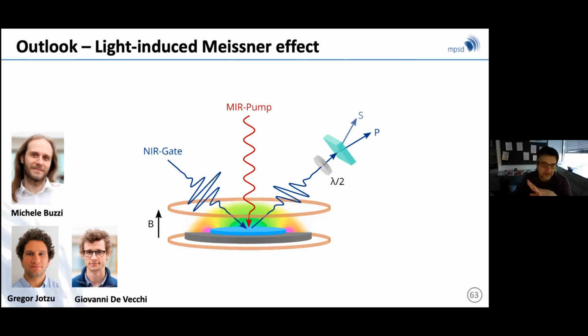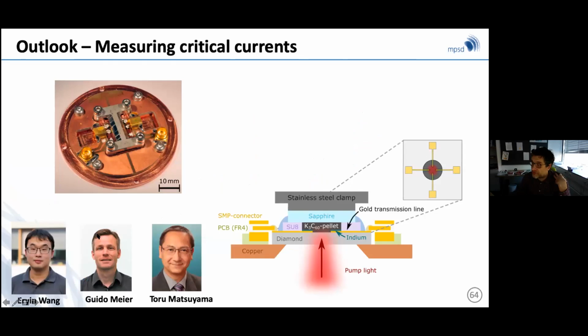Of course, the light-induced state, for a number of reasons, is harder to do, so I won't belabor this any longer. And also for this, we have measurements already. This is Eryn Wang, who has been able to show that the same transport measurements that we use on nanosecond timescale, but also at femtosecond timescale with other techniques that I have not had time to discuss here, we've been able to show critical current measurements in the light-induced state. So we can find already basically that if the current that is used to probe the sample becomes of order HC2, then I can generate something that looks like a depairing field, and I have a very clear nonlinear critical current response.